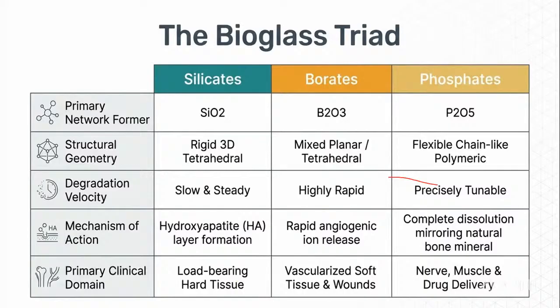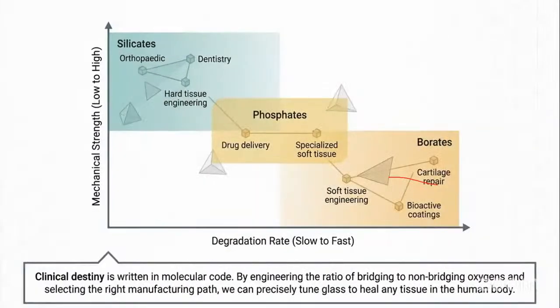But if I have to create a rapid angiogenic result, ion release, that is, to create blood vessels, then I will go with a borate as well as a phosphate network, which is called borophosphate glasses. And if I have to completely mimic the nature of bone, then I would definitely go with the phosphate glass network.